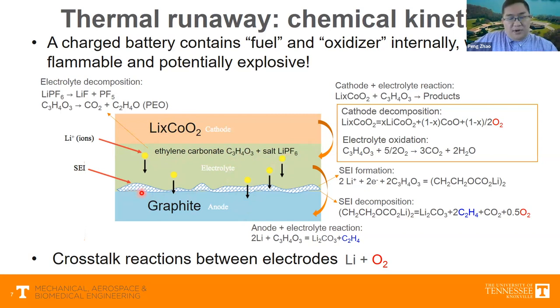What typically happens during thermal runaway is at elevated temperature conditions, the SEI layer that formed at the first cycling tends to decompose. Once it decomposes, it generates lithium carbonate, ethylene, CO2, and oxygen. And the lithium within the anode particles can directly react with the electrolyte. So that becomes a major exothermic reaction. At the same time, your cathode can decompose, become reduced metal oxide, release oxygen, and this oxygen can further combust with the organic component in the electrolyte.